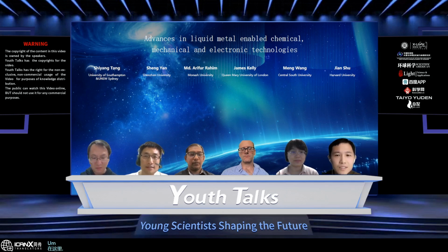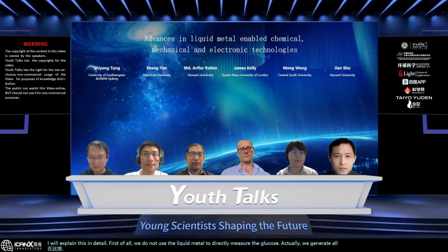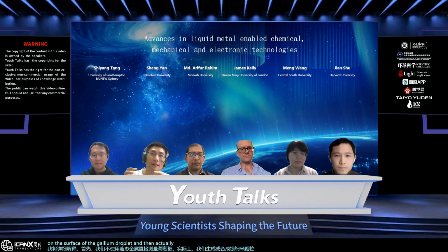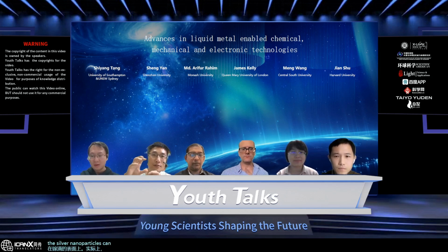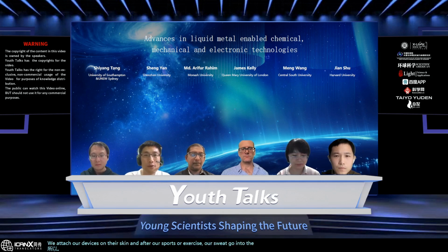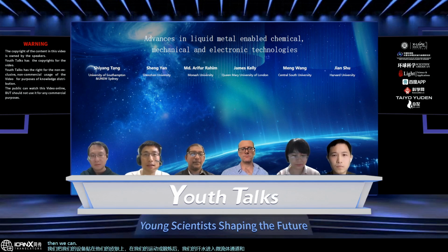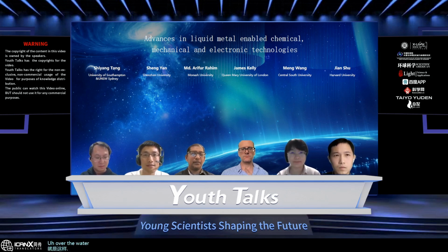Here, I will explain this in detail. First of all, we do not use the liquid metal to directly measure the glucose. Actually, we synthesize silver nanoparticles on the surface of the gallium droplet, and the silver nanoparticles can capture the glucose. We attach our devices on the skin, and after sports or exercise, our sweat goes into the microfluidic channel, and then we can do the measurement in sweat. So that's how our device works.